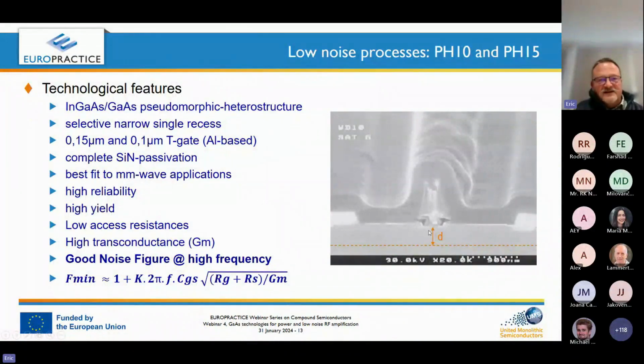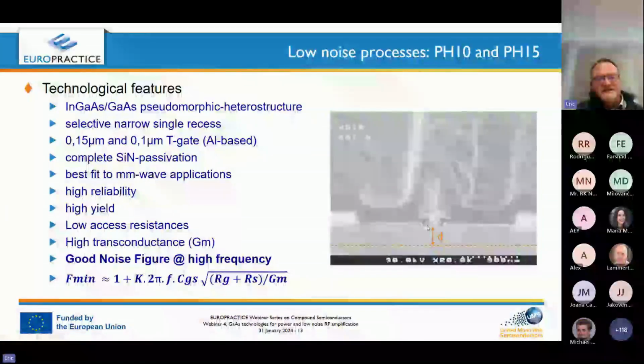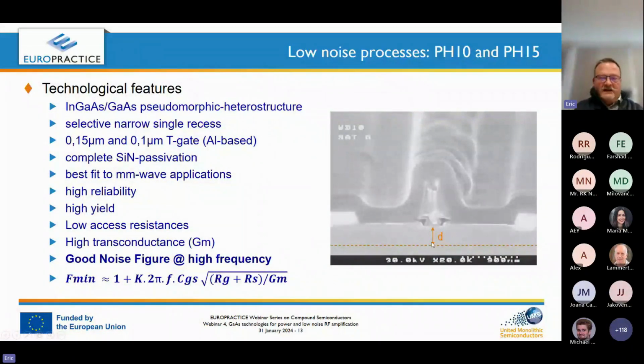You can see here something very important in our GaAs technology. It's a recess. A recess is a chemical etching near the gate in order to control exactly the distance between the gate and the 2D channel. And you remember what I mentioned a few slides before, through this distance, you can control all the critical parameters of the device. We also call that a T-gate. Why? Because it's more or less a T. You have the foot and then on top the horizontal bar of the T.